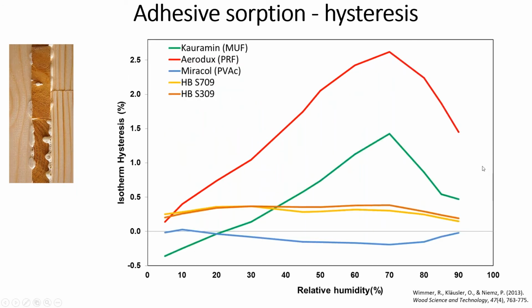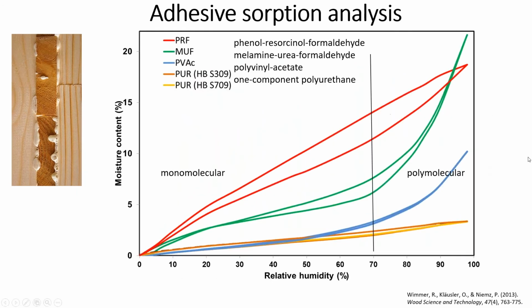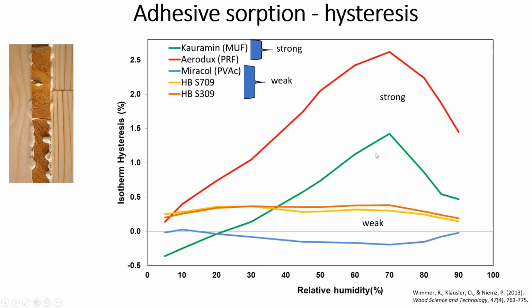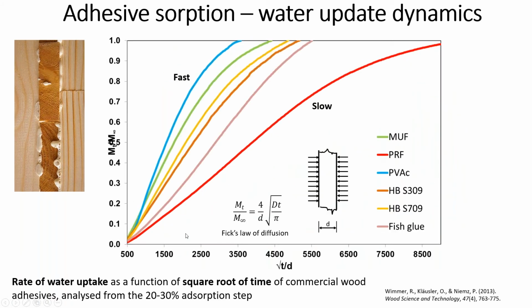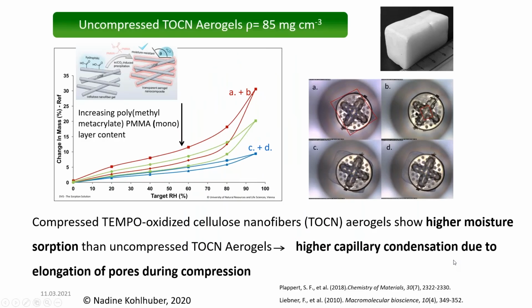because in a sorption isotherm, I'm going back to that slide, you're looking at the static curve, because all the points that create these lines are where the system is in equilibrium, whereas this is the dynamics of uptake of water relative to the time that is spent on this.